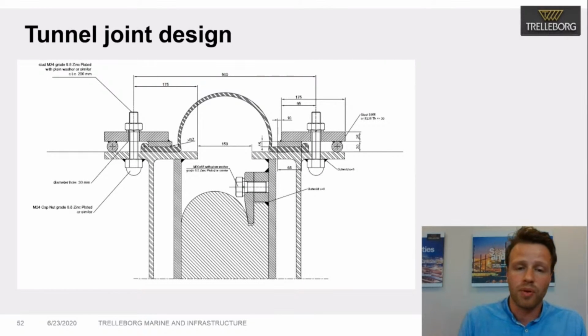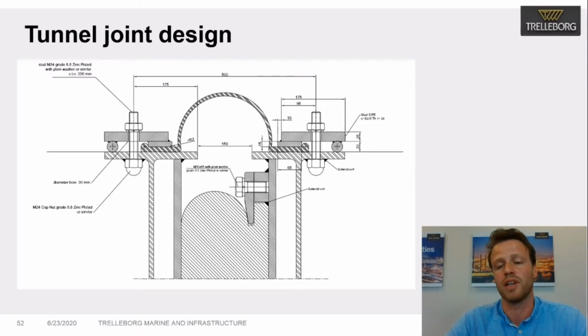So here you can see a typical cross-section of the omega seal. On the graphic below, you can see the GINA seal being compressed, and the omega seal is clamped in place later on. What most of the time happens is that those anchors are already pre-installed on site, and when the omega seal arrives on site, you only have to clamp it in place, and you have to determine what the clamping force needs to be to make sure that the omega seal will perform accordingly. And during the tightening of those bolts, you have to take into account the relaxation. So most of the time you have to retighten them after 10 days, after 2 weeks, and then most of the relaxation behavior is taken into account.